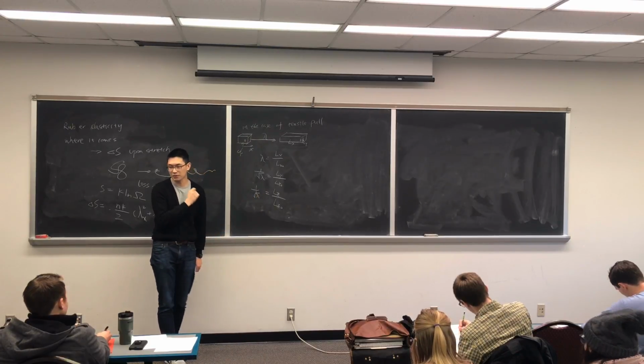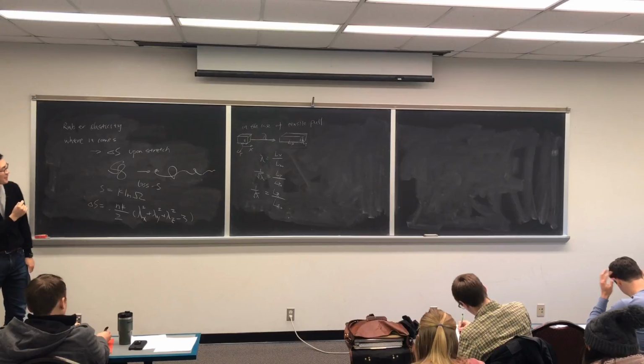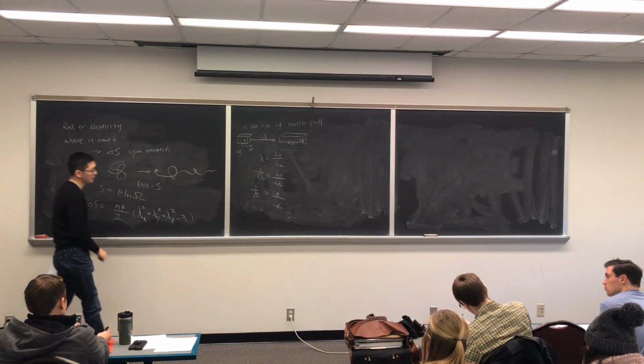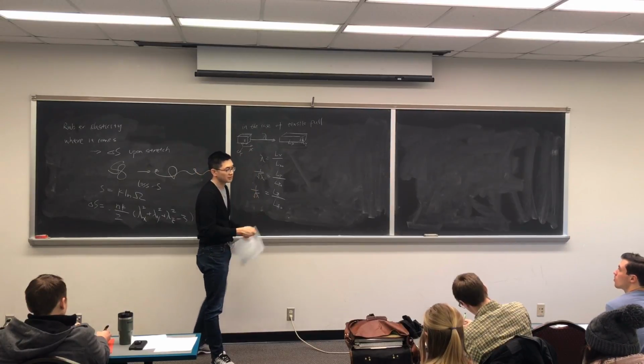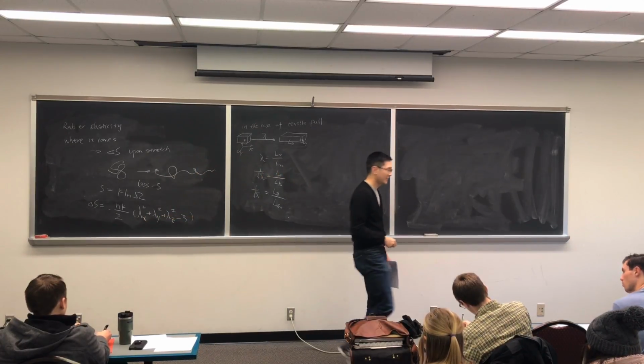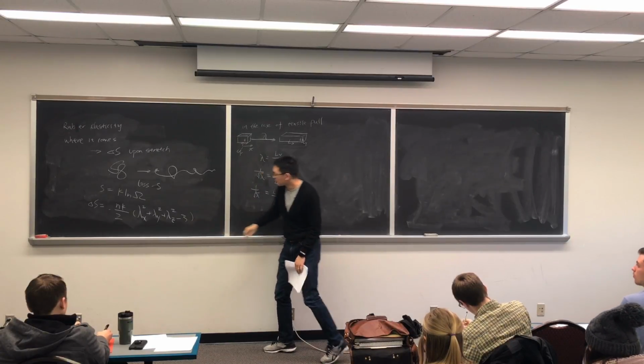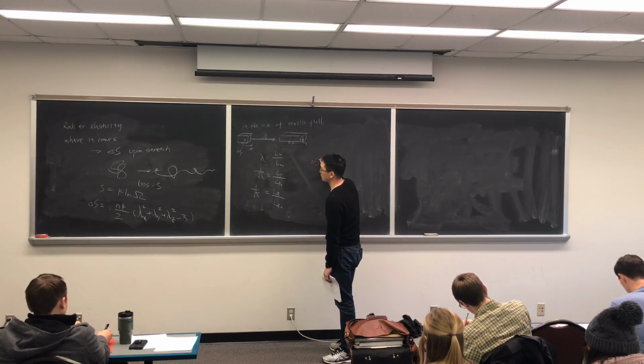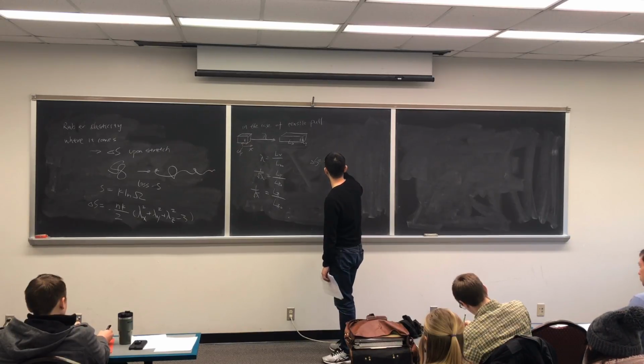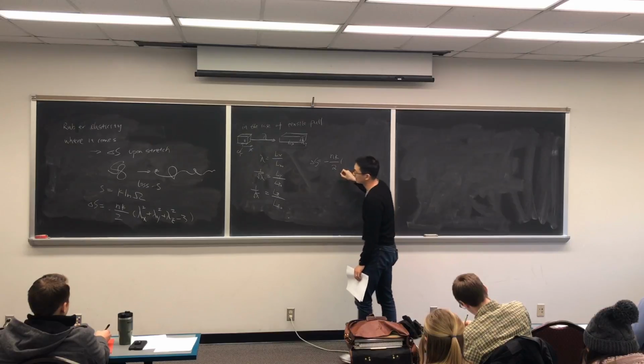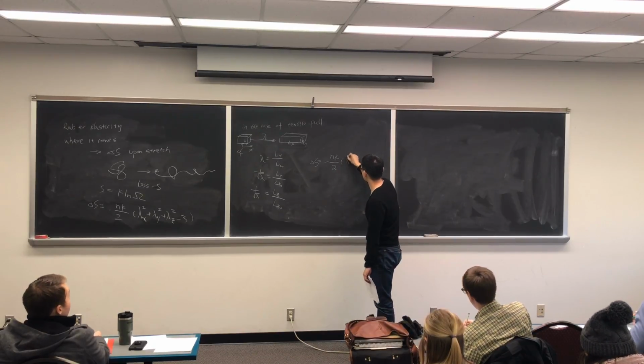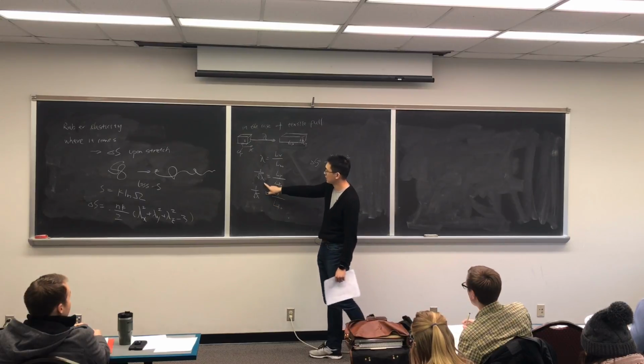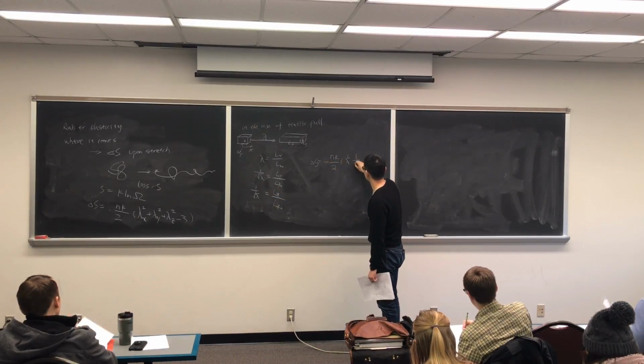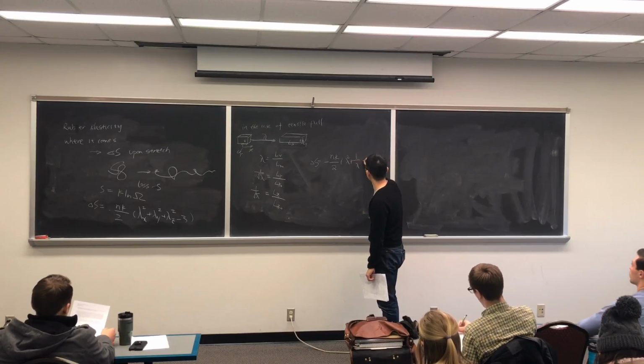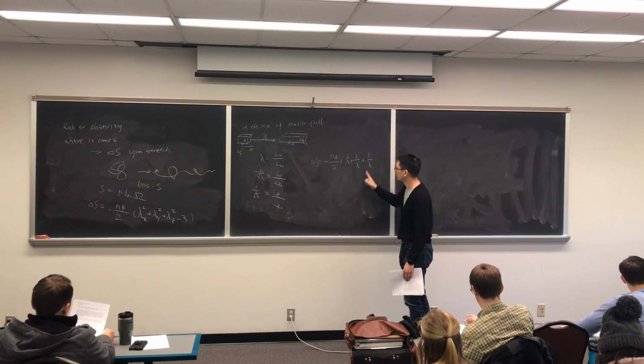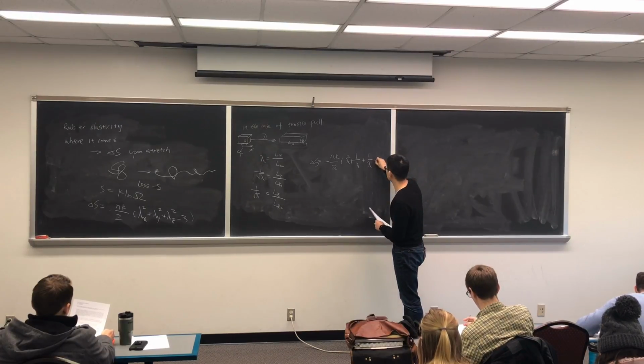So we talked about this special occasion, how your delta S would be changed. In this very special unidirectional pulling methodology, your lambda x, lambda y, lambda z can be written in a much simpler form, where you divide by 2. Now lambda x squared is going to be lambda squared. Lambda y squared is going to be 1 divided by lambda. And you're going to plus lambda z squared, it's again 1 divided by lambda, and minus 3.